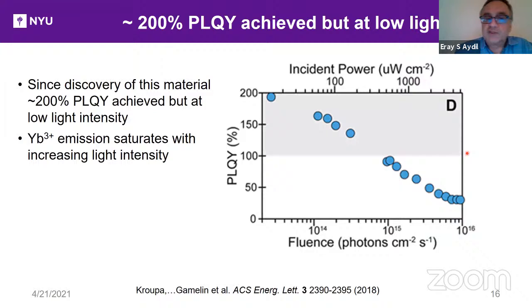So since the discovery of this material, near 200% photoluminescence quantum yield has been achieved. And in particular, at University of Washington, Gamelin's group has published a series of beautiful papers looking at this particular material, cesium lead chloride, as well as bromide variants, looking at the mechanism and studying the ytterbium doping of nanocrystal dispersions, as well as films made out of those nanocrystals.